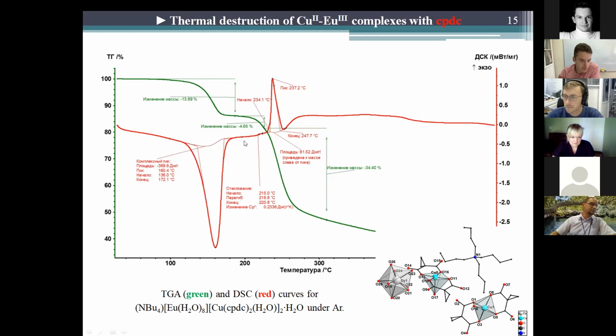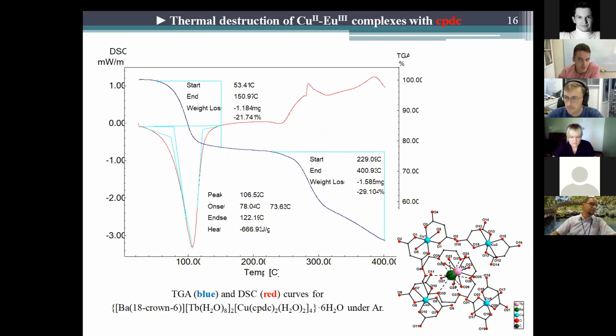Further, at 215 degrees, the glass phase formation occurs accompanied by the weight loss that corresponds to the composition of organic fragments of the complex. The copper-barium-terbium complex with 18-crown-6 starts to decompose already at 53 degrees. Then there is one endothermic peak in the DSC diagram that corresponds to loss of all water molecules here. And then the sample is stable up to 229 degrees, when its organic part starts to decompose.